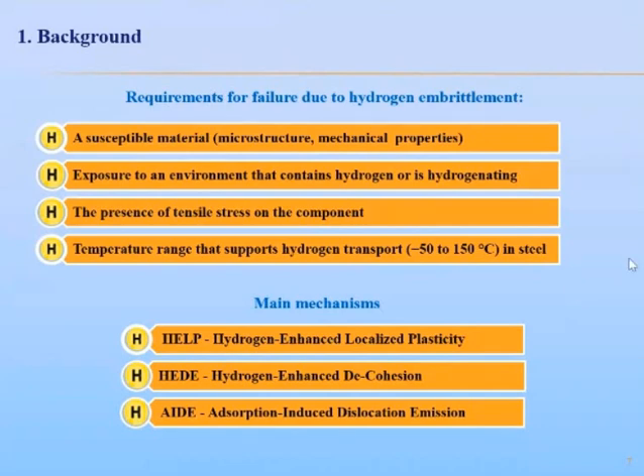And a hydrogen-enhanced decohesion mechanism is based on the weakening of iron-iron intermetallic bonds at or near crack tips due to a decrease in the electronic charge density due to the presence of hydrogen in the crystal lattice in interstitial sites. That then favors an easy tensile separation of the atoms. And a fracture surface should appear basically featureless with few cleavage steps and tear ridges separating decohesion regions.